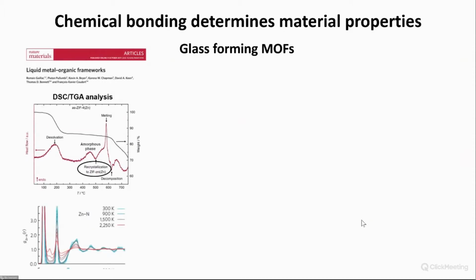And one example of this is MOFs. And this is a nice area of MOF literature. I think these glass-forming MOFs, that normally you'd think an organic thing would just decompose when you heat it up, but you have these special MOFs that can actually melt, and then you can cool them down and you have a glass. So in one example here is these ZIFs, so the zeolitic imidazolate frameworks. If you heat them up, they first lose their solvent, and then they become amorphous. And then you're saying, okay, then they probably start decomposing. But no, they recrystallize again in a new, very dense structure that in the literature is called the ZNI structures.